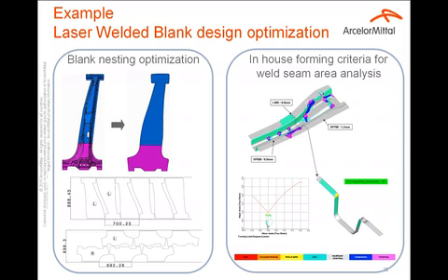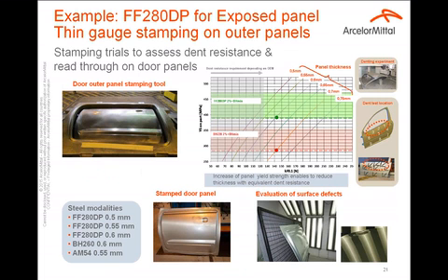Last example is the laser welded blank design optimization that you can run in this third phase, by first a blank nesting optimization to increase the material utilization rate, which is of course very important for cost reasons, and also in-house forming criteria developed for weld seam area analysis in between both sub-blanks along the weld seam. Then we can also run stamping trials.